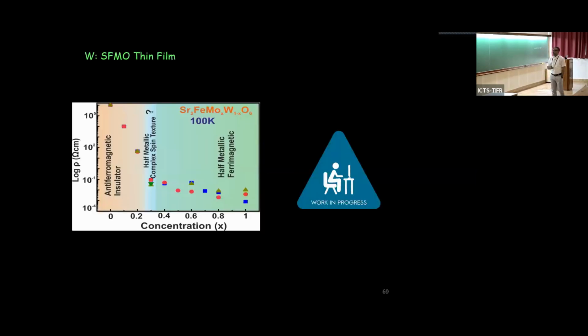We started working on this and we found it is not only about how stable it is, it has a very rich phase diagram. Recently we made this phase diagram. So this is the concentration of molybdenum doped in tungsten. If it is SFMO, this is conducting, so half metallic and ferrimagnetic or ferromagnetic material. But if you go towards the iron tungsten side, it is an antiferromagnetic insulator. And there was a lot of debate about the origin of this metal insulator transition, and Didi has a paper in 2000, I believe, that shows there are two possibilities: a valency fluctuation in addition to the percolation threshold, which gives rise to this metal insulator transition.